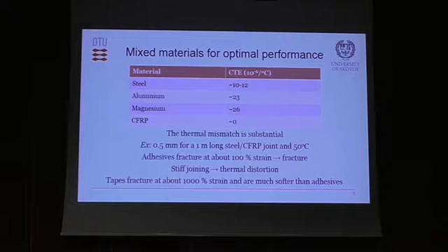A structural tape can withstand typically of the order of 1,000% engineered strain before it fractures. It is enormously tough. And it is much softer than adhesive, so the stresses are much smaller, and the thickness is much smaller. The thermal distortion will be much smaller, and the stresses in the joint will be much smaller. But will they actually be able to withstand any load? That is the question.